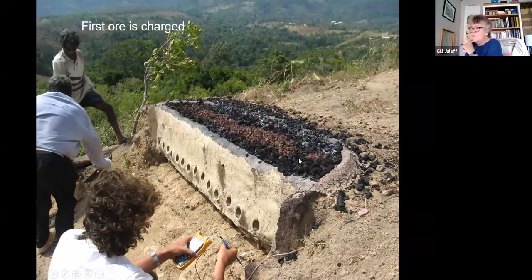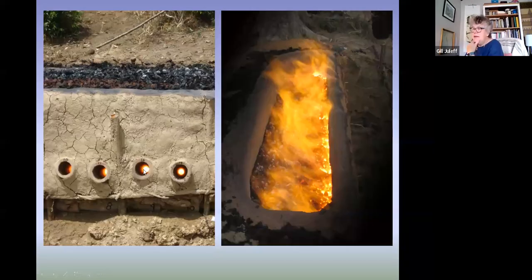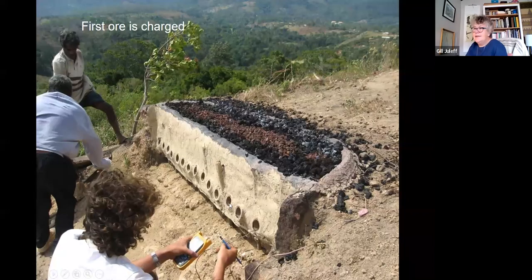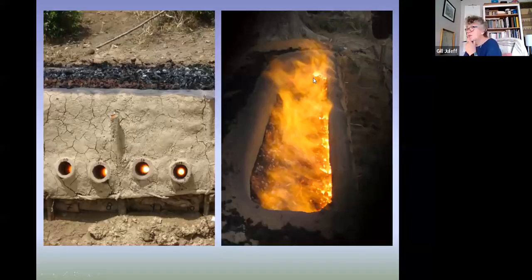So this is what it looks like when it's really beginning to get going. And you can see by looking down at the tuyeres that we've got very good high temperatures. We're getting into yellow heat, even white heat. And you can see in the short distance at the top of the furnace, we've got quite a steep temperature gradient between the temperature inside the furnace and the temperature of the burning charcoal on the top. If we look down from the top, we can also see that we've got the highest temperatures focused and concentrated behind the front wall. And again, you can see that black line of scorching along the top of the front wall.